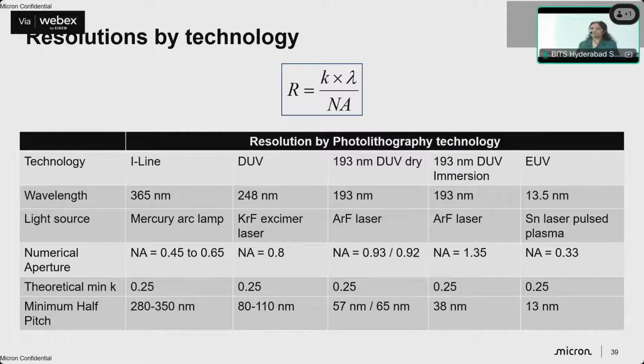Just to give you a cheat sheet of where we typically go with feature size for certain rules: 193 nanometer immersion lithography can get you as low as about 38 nanometers. Really, really low. Now, if you see 193 to 13.5, there's a wide gap of wavelength that we are looking at. And actually, 25 years ago, there was a push towards 157 nanometer also, but at that time, immersion lithography came into effect, and double patterning came into effect, where you would take the films and do some post-processing steps to actually shrink down the pitch. So the 157 nanometer program was rolled off. But now 13.5 nanometer is back in evaluation.